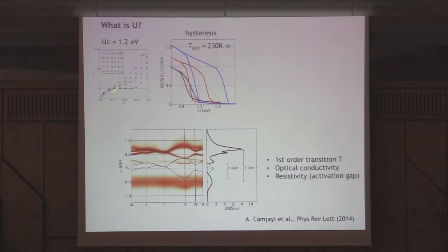So if U is 0.9, this is the N versus mu. So the slope here at 1 is the compressibility. So this is a compressible state. It's metallic. Then the compressibility starts increasing, and then you get a plateau. When you get a plateau, you have an incompressible state, which is the indication of the presence of a Mott insulator. You change your chemical potential, and you cannot dope more electrons to the system. So you see, by the time you hit 1.3, you have a well-developed plateau, therefore a Mott gap. So we fix U to be 1.2, the blue line there.